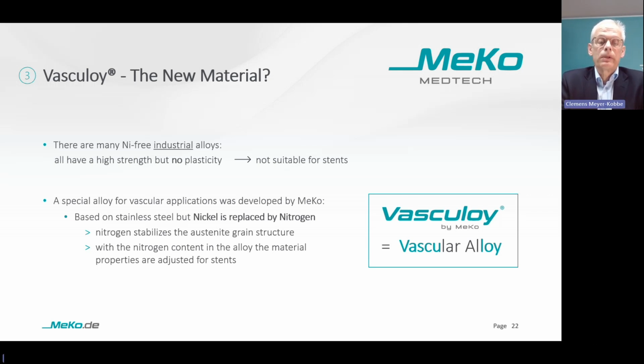The nickel content, for example in stainless steel, improves the stability against corrosion. And therefore, also for the other alloys, nickel is an important component in the alloy. It is well known that nickel can be replaced by nitrogen. First, this sounds very strange, as nitrogen is a gas. How to get it into a metal alloy? This is possible during the melting process of the alloy under a high pressure nitrogen atmosphere.